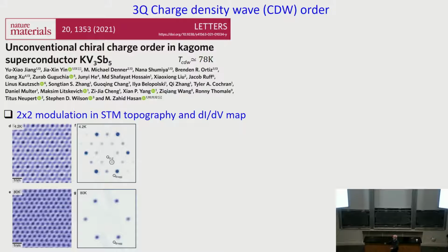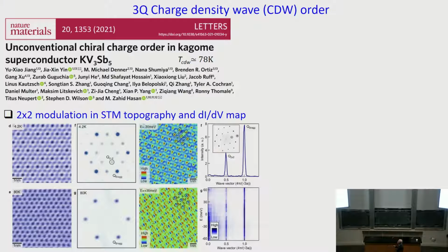But if you go to lower temperatures, then there are additional Bragg peaks emerging. That shows there are additional structures in this material, and these peaks sit at half of the Bragg wave vector. So this is a sort of 2a0 by 2a0, 2 by 2 ordering, 3Q ordering of the charge density wave state. You see that in the dI/dV maps, which are density of states maps, right?